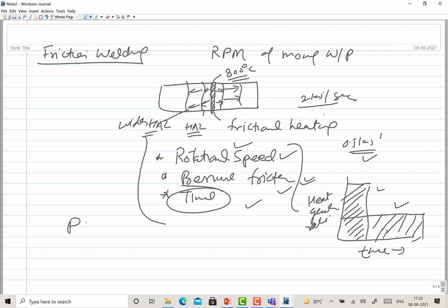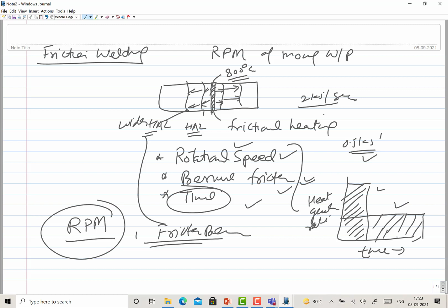So the RPM, rotational speed, and say the pressure, the friction pressure that is being applied. These two will be determining the rate at which heat will be generated. So considering the system capability, considering the forging pressure that you have to apply, say there is a limit on the friction pressure that we normally apply. So what is the independent parameter left? You can rotate the sample at say 500 or 1500 or 4000 RPM. That will be changing the rate of heat generation significantly.